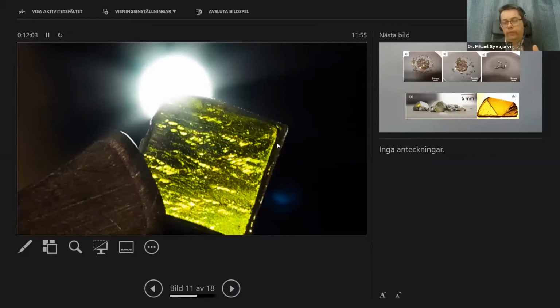So for the power devices, there is a particular silicon carbide format, a polytype, which is called hexagonal silicon carbide. That is the one which is recognized for the market and so on. And silicon carbide is built from silicon and carbon atoms. So you build it and then you have different types of silicon carbide. There's maybe 200 different versions, and there's one which is very mature. But then you have the little brother in the silicon carbide family, which is called cubic silicon carbide. This has traditionally been very difficult to grow because there are more challenges in this process for the growth of this material. But this is what Valdas came into.